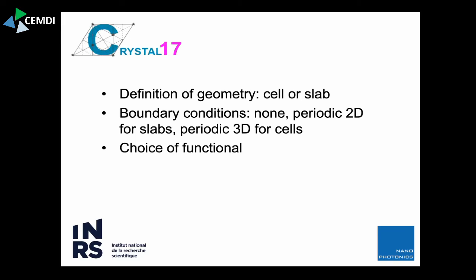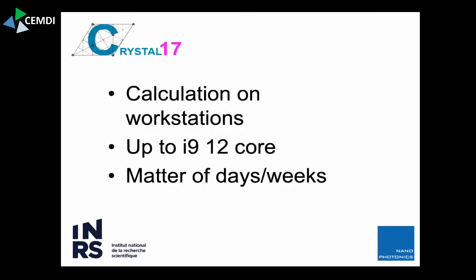And then we choose the boundary condition, either none if we talk about nanoparticles, periodic 2-dimensional conditions if we try to simulate a thin film, or periodic toroidal 3-dimensional conditions for solids. And then we choose functionals. And honestly, this is very much done in a way that we pick several. We compare the results, and not having the knowledge which one would be the most appropriate for scientific reasons, we look for consistency. If the results don't spread too much, we get some confidence in the findings. But there is always some scattering. So please take all the numbers with a grain of salt. This is not within wave number precision, obviously not.